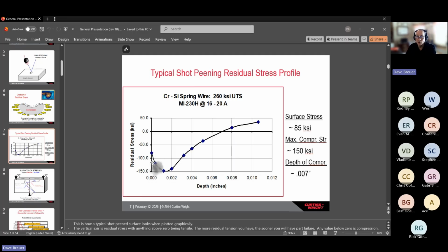And the residual compressive stress at the surface has a significant effect on fatigue life. So if I were to draw the dual peen - let's just say I take the curve here and extend it right there - the second peen doesn't change the bulk, the peak stress, or the depth here. It just changes the surface compressive stress.